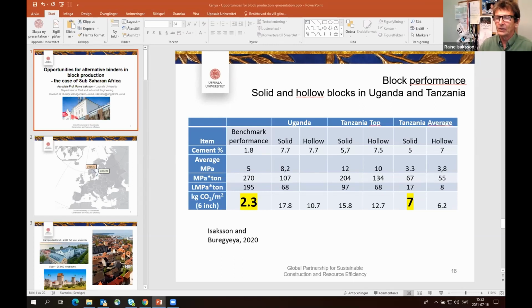So hollow blocks are better, but only when you are at the standardized and good quality blocks. When we look at Tanzania, 90% of the blocks are solid, and this is an average we have found, but in many cases blocks are even of a lower strength, but still providing the functionality. So the low performing solid blocks have the lowest carbon emission, and they also are the cheapest ones. Hollow blocks here, in this case, we found some which were at the same level, but they normally are more expensive. They are more difficult to produce, more breakage.